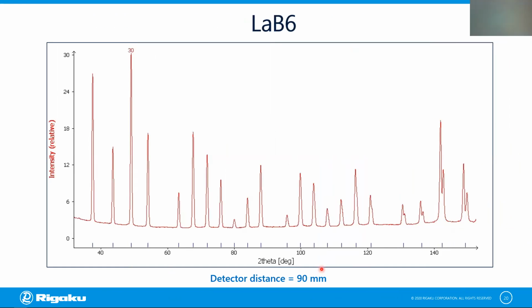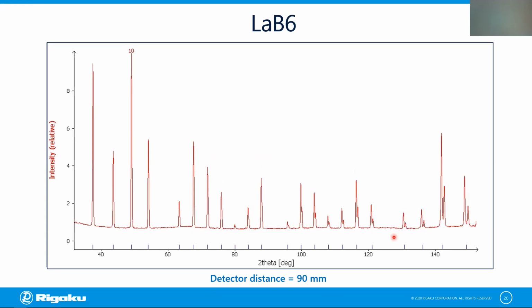In terms of the intensity versus 2 theta plot, this is what I got with the full beam. Nice spectrum, no problem, with the alpha 1, alpha 2 split for the high resolution peaks here. But with the lowest beam divergence, this is what I got. Now I've got more peaks at lower resolution that also show the alpha 1, alpha 2 wavelength split.